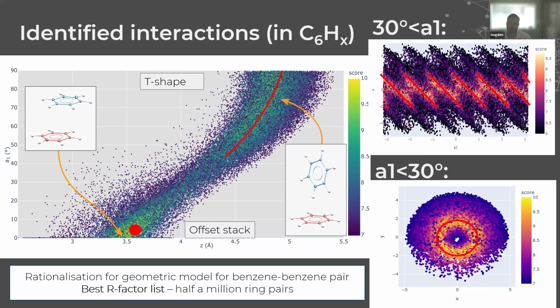If we instead focus on where A1 is less than 30 degrees, so this is closer to being an offset stack interaction, you get this donut shape where you have a hole in the middle at XY equals 0, which is telling you they don't like to sit directly on top of each other, unless you have the case where it's hexafluorobenzene and its electron density is very much different to a normal benzene.